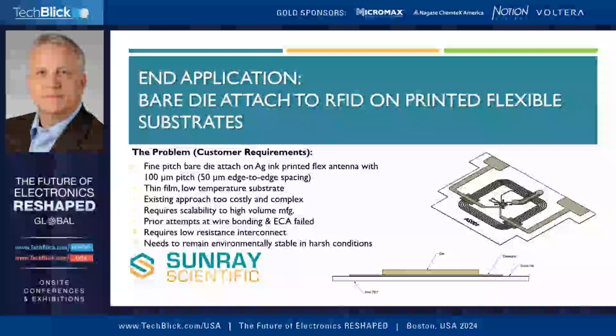So they had tried initially with an ECA material, and they had looked at ACF, but couldn't do ACF because of the thinness of the die and the polyester film. The pressure was too much. And they even tried wire bonding. That was going to be very expensive, and it was a much slower process for them, so that wasn't going to scale well. And they couldn't get the bond strength of the component. And the ECA also failed because of pitch issues. They needed low resistance interconnection for the performance of this tag, and it had to remain very environmentally stable because of the harsh conditions it was going to be exposed to, which could include immersion in ice water.